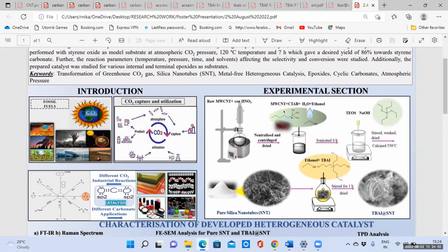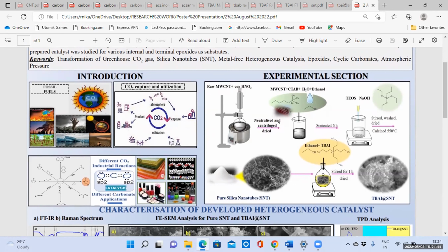Beginning with the experimental section, raw multi-walled carbon nanotubes were oxidized in the presence of nitric acid at 80 degrees for 6 hours. Then the oxidized functionalized multi-walled carbon nanotubes were neutralized, centrifuged and dried, and were used as a template for preparation of silica nanotubes, where multi-walled carbon nanotubes were treated with CTAB, ethanol and water system and sonicated for 6 hours. After the sonication, TEOS was added dropwise and stirred, washed and dried for 24 hours, and later calcined at 550 degrees to obtain pure silica nanotubes.